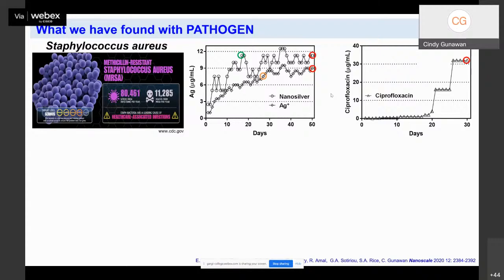Now, to validate resistance development, we took these cultures at the end of the prolonged exposures. We then grew these cultures on an agar plate that contained the respective antibacterial agent. Then we picked the resistant colonies, or colonies that had been growing on those antimicrobial agar plates. We then cultured these colonies for several days in an antimicrobial-free liquid medium, so no silver and no antibiotics for several days. The reason for this is that we would like to isolate a cell population that has developed a stable adaptation phenomenon to these antibacterial agents, excluding any subpopulation of the bacteria that only have a transient adaptation response.